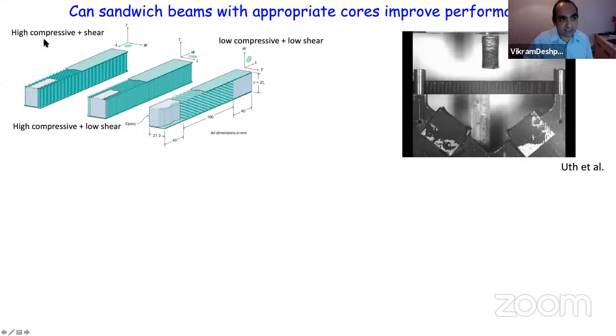So I can make a core that has high compressive strength and high shear strength. I can make a core by rotating it in the T plane, having a high compressive strength but a low shear strength. But then if I rotate it completely, such that it becomes like a hexagonal honeycomb where W is now the in-plane direction, you can see that I've changed the axes such that W is now in the vertical direction, then I've got a core which has a low shear strength and a low compressive strength.